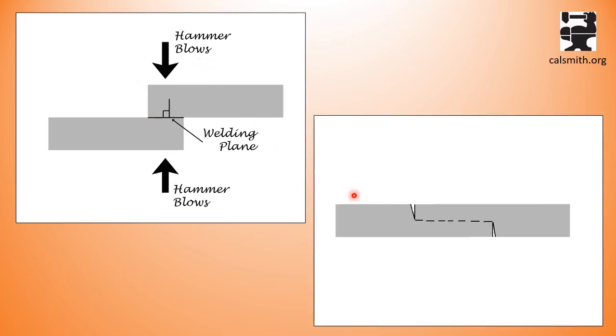We want these pieces to blend in, and we want them to blend in such a way that the final weld is the same as your parent stock. So looking at these two pieces lined up, you can see that not all these edges that are going to be pushed down into the other piece of metal are lined up in the welding plane. In fact, these are parallel to your hammer blows and become a shearing plane.